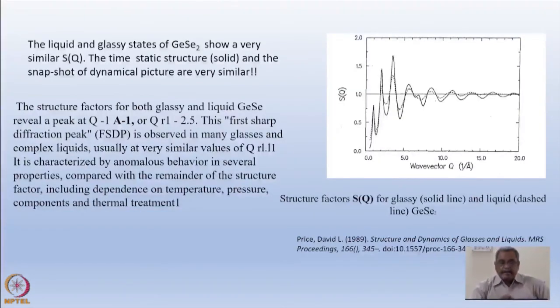Now the liquid and glassy state, as I told you earlier, I promised you that the snapshot picture of a liquid is very similar to the amorphous structure in a solid. So this is experimental data for germanium selenium glass, the liquid and glassy states. You can see the S(Q) is very similar, except the liquid, which is a dashed line, is slightly less intense, but the structure is very similar.